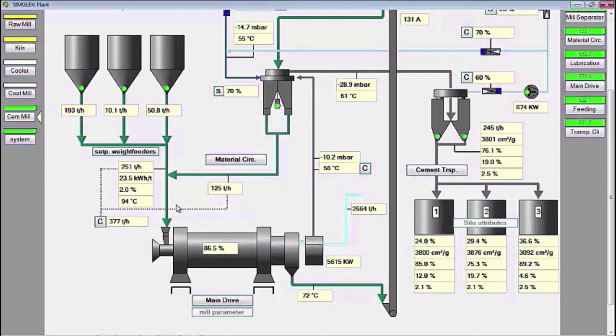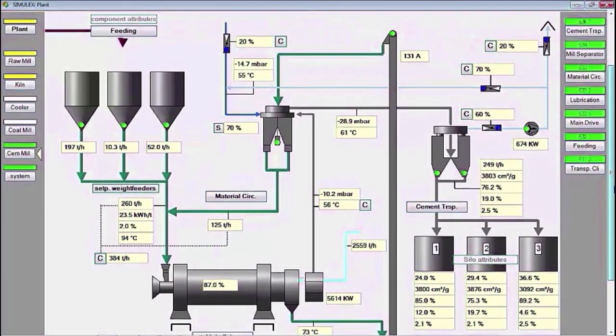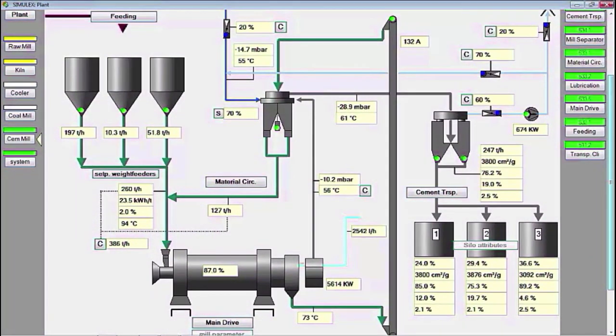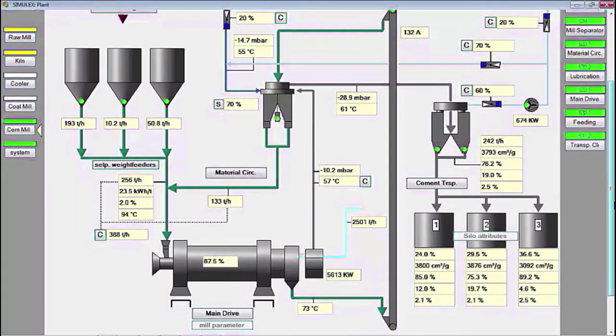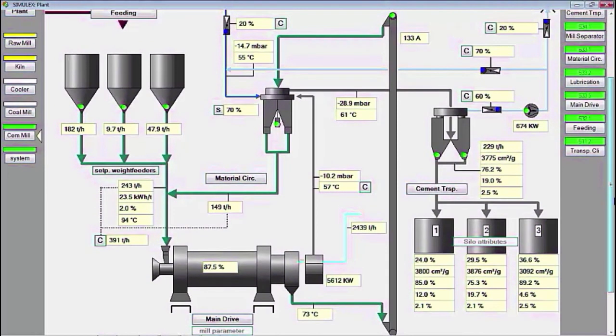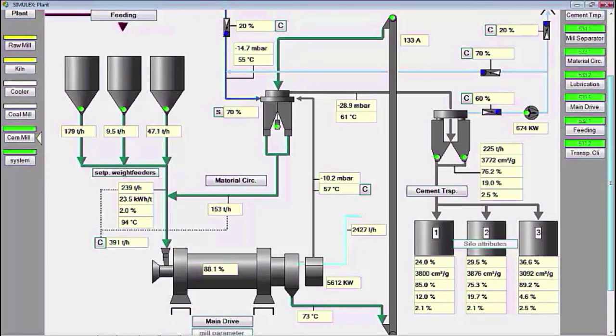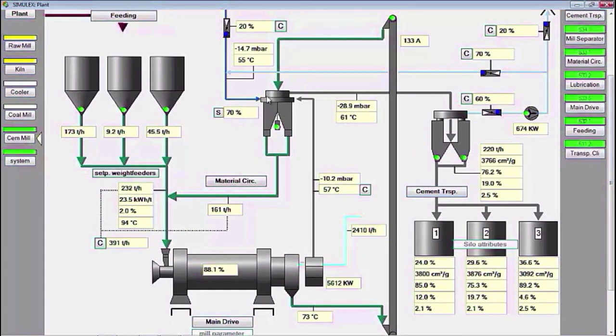That was the explanation about the operation of the ball mill that does not use a pre-grinder. When viewed visually, the residue at 45 microns cannot be reached below 6%, but Blaine can be achieved according to the standard, meaning that there is something not quite right in this grinding system, for example the composition of the steel ball, the level of grinding media, and the thickness of the mill liner which has started to wear out.